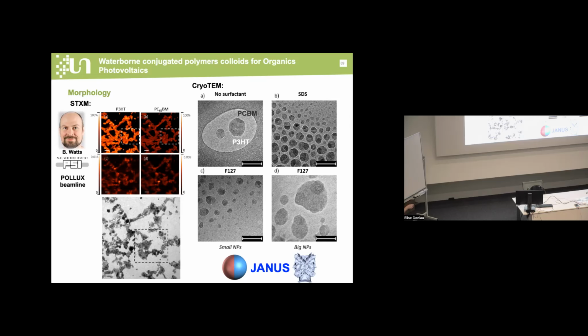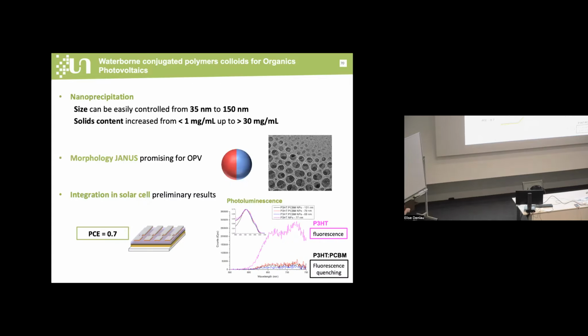So here you can see that the darker contrast is the PCBM part, which is more electronically dense than the P3HT, which appears lighter in the picture. So as a conclusion to this part, we can synthesize well-defined nanoparticles whose size can be easily controlled by tuning the dispersion features, and we see for the first time this Janus morphology, which is a morphology very promising for OPV application. And first preliminary results on the integration in solar cells show that the efficiency could be measured, but as you can see, at the moment it's rather low. So we still have to go further in this work.